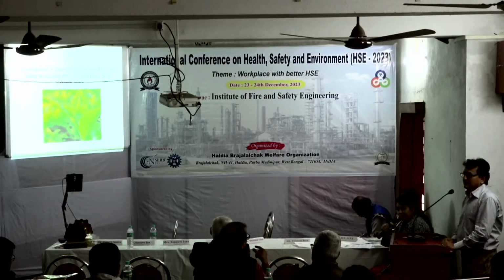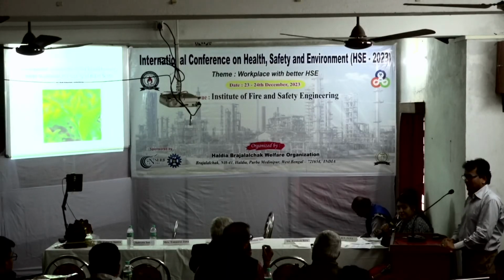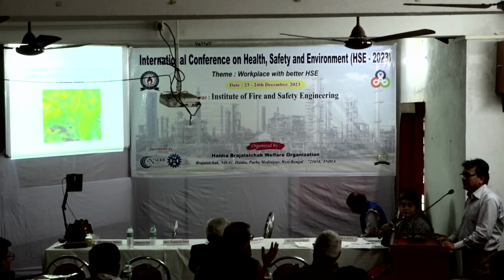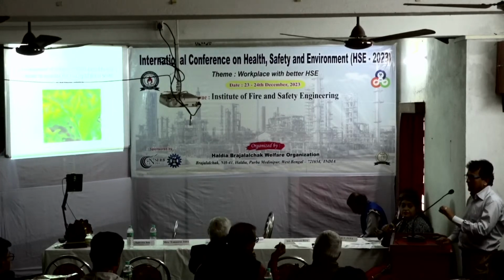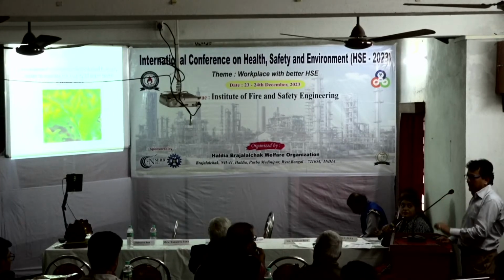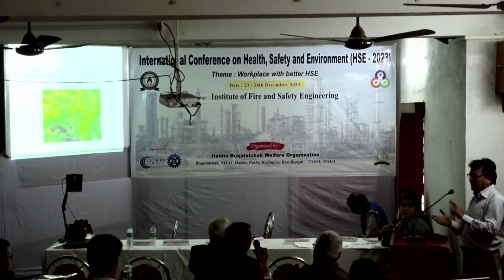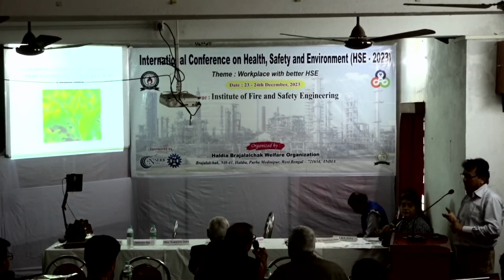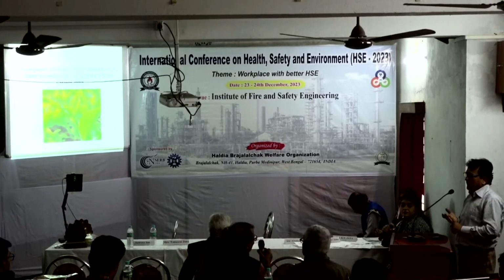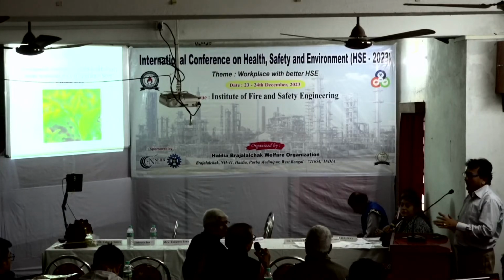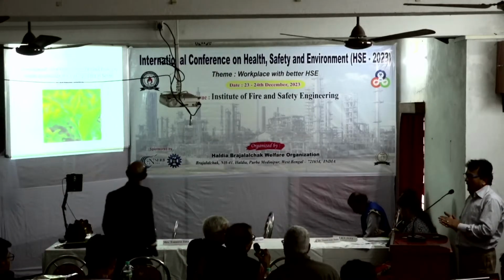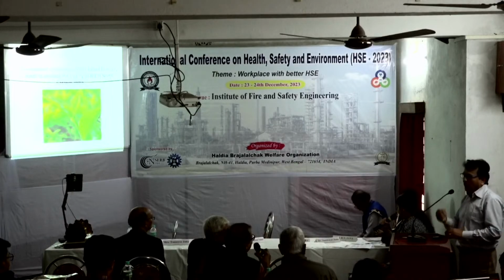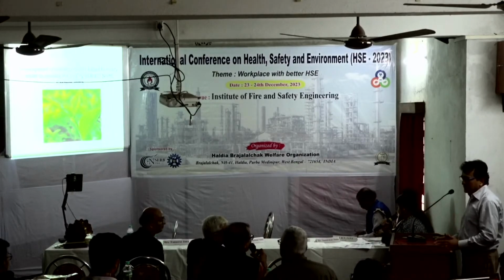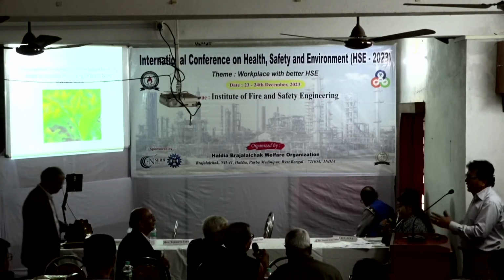So your ceramic sensor, but you start with alumina, gamma alumina. Is gamma alumina purely a ceramic material, no other things? So purely it is an alumina compound. Actually, alumina, Al2O3, has a lot of varieties: gamma alumina, alpha alumina, theta alumina, beta alumina. The idea of ceramic is a little bit wider. Actually, alumina is a broad base of the ceramics. You go to the castables, you go to the alumina bricks, everywhere alumina is required.